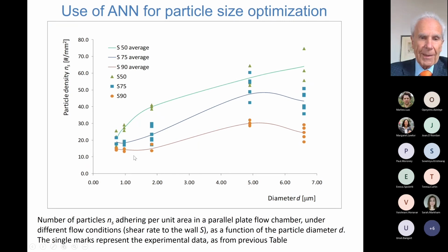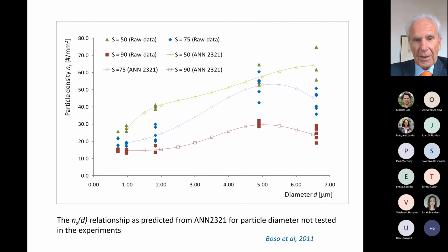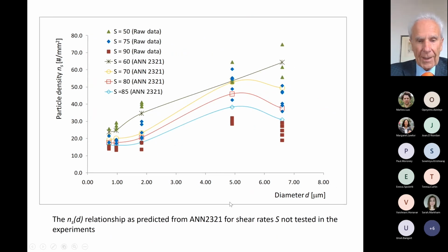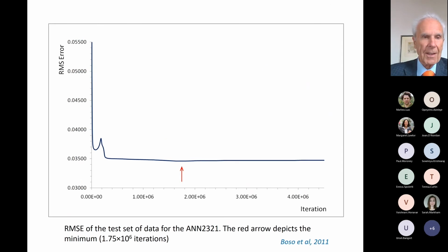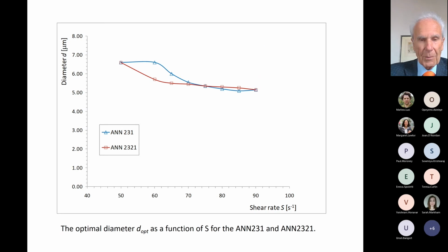And here you see the experimental data you get. Again, here it's difficult to get a picture. I mean, these are mean values. However, once you have trained the artificial neural network, we are able to predict the relationship between diameter and the density of particles which adhere to the endothelium for different values of the parameters. And here we can get the relationship for shear rates which are not tested, and again for the diameter. So we get out now quite a more complete picture. For instance, just from the training of the neural network, we get out the optimal diameter for different shear rates.